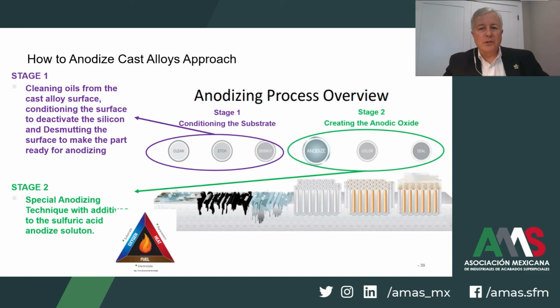This slide is a good general overview representation of the 2 stages that are needed for successfully anodizing cast alloys. In the first stage, we've introduced a new surface acid preparation process that demonstrates some improvements with the removal of the silicon intermetallic zones that exist in the layer and throughout the surface. In stage 2, we've developed some new organic additives in the sulfuric acid anodizing chemistry that help overcome the difficulties with the silicon. Only using the additives in the anodizing process does improve the performance of the thickness layer and the oxide layer, but for a greater density, harder, more uniform process, we need to incorporate stage 1 and stage 2.